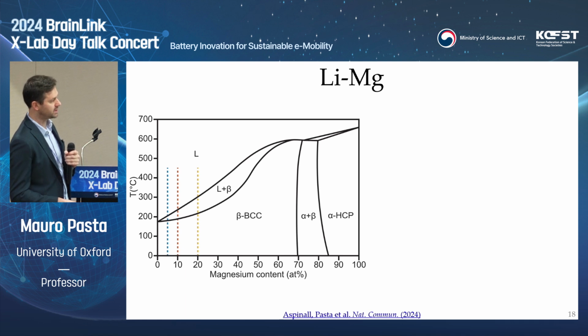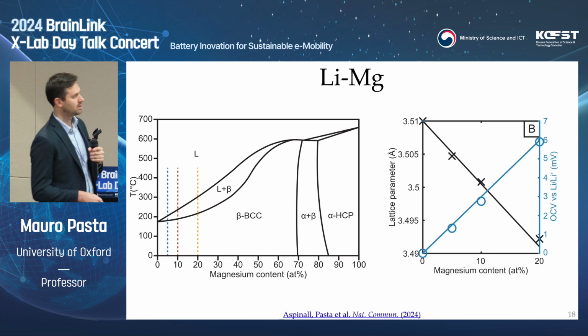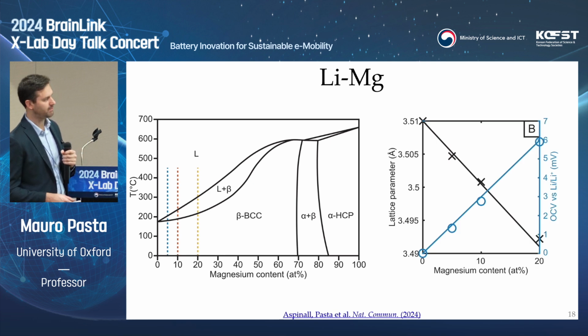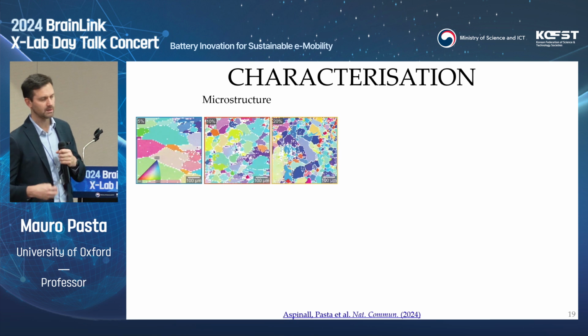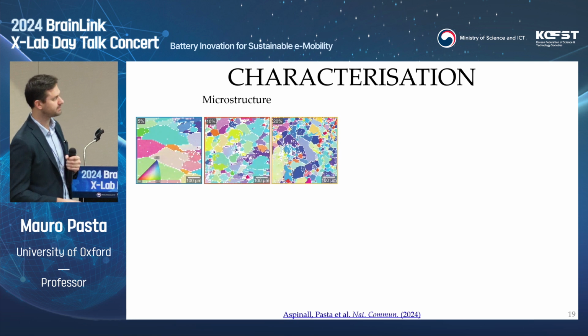Atomic percentage of magnesium in magnesium-lithium. So you can melt them, solidify at different rates, and therefore have a certain level of control on microstructure. You can perform XRD, OCV measurements, and prove that you actually form what you wanted to, but we do a quite substantial characterization. We characterize the microstructure.